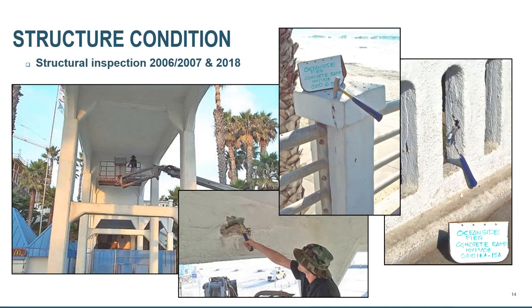And so what is in that concrete, this is 13 years ago from our testing, was that we had chloride contents or salt contents in concrete up to 14 times that threshold. And part of that problem is that salt remains, it's still in the concrete. And so these problems of this corrosion will continue to occur.